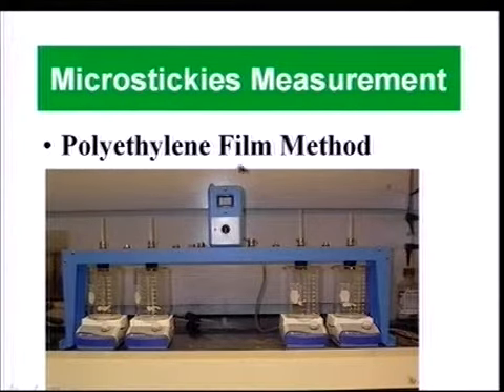Venditti and associates at North Carolina State University used the beaker method to determine the amount of microstickies deposited on polyethylene film. So in this case, you take 4 different beakers, put your pulp sample in each of the beakers, and heat it up to about 165 degrees Fahrenheit or thereabout, and put in pre-weighed pieces of plastic film. For half an hour you stir it, let the microstickies deposit on the plastic film, and then you take out the plastic film, rinse it with cold water, and measure the increase in weight of the plastic film.